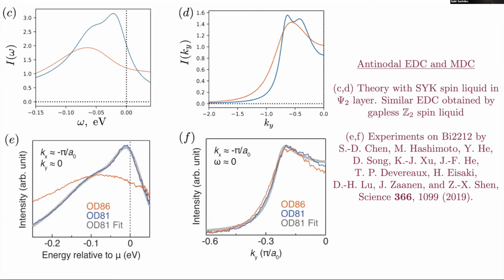So here, in fact, in this case, we took an SYK spin liquid because it's just spin correlation and momentum independent. It's much harder to compute it in a momentum dependent spin liquid. We haven't done the MDC in that case yet, but it's not so sensitive to those details. I can't tell you what the spin liquid is, but if you take some reasonable model for this chi spin liquid, you get the line shapes, both the MDC and the EDCs, and they agree reasonably well. Okay, with this subsequent later paper by ZX's group, which was also referred to this morning.